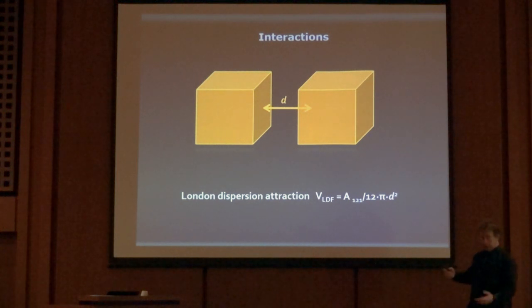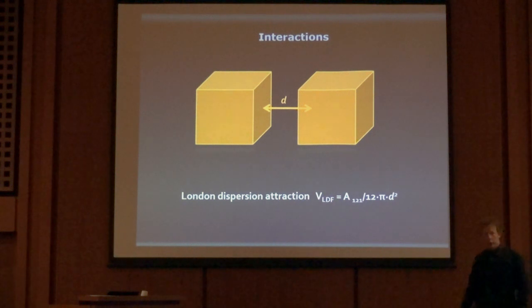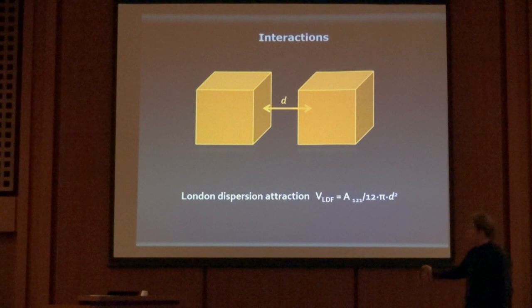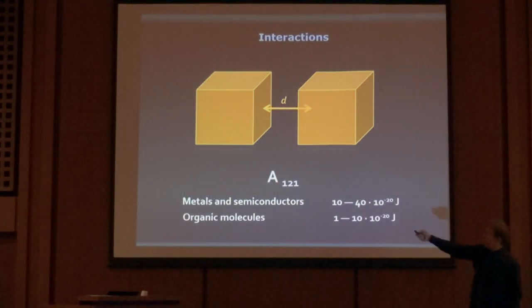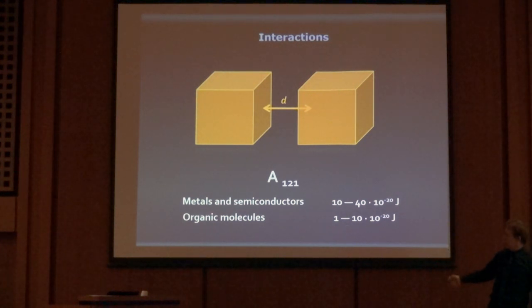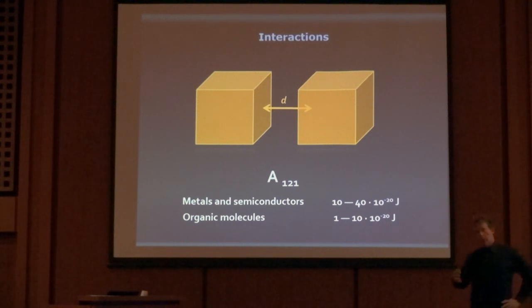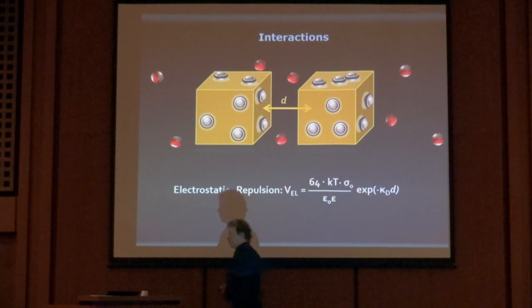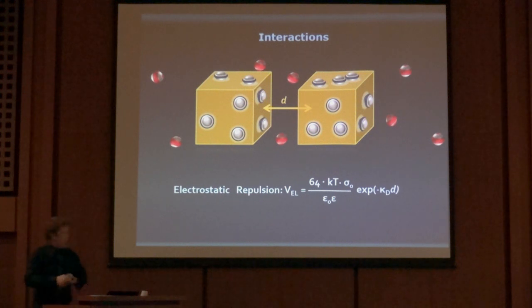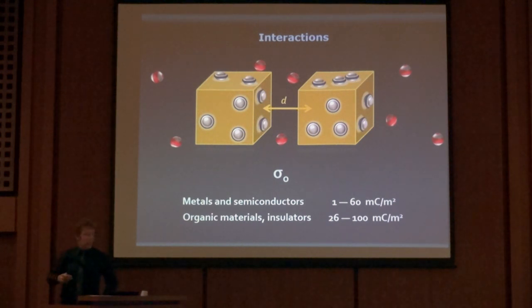So, the London dispersion force is, in first approximation, proportional to the so-called Hamaker constant, A121. If we look at the organic and inorganic materials of the same size, of the same shape, we will see that for metals and semiconductors, we observe several times increase in the value of the Hamaker constant. If we look at the other case, at electrostatic interactions, they are in the same approximation proportional to the interfacial potential here. There are a lot of complex concepts encoded in this cartoon, but if we again look at the value of sigma naught for the metals and semiconductors, we will see that for organic materials, it's actually higher.